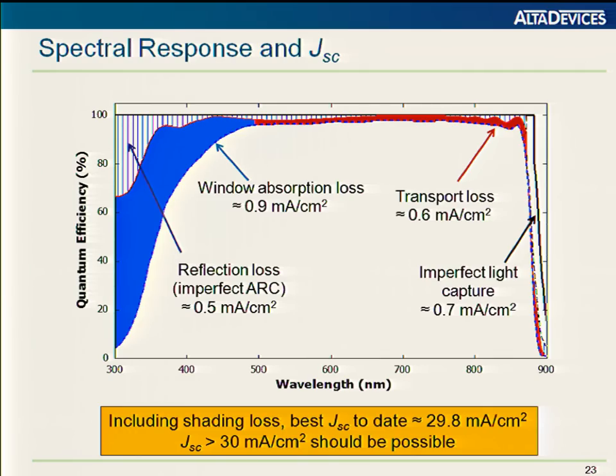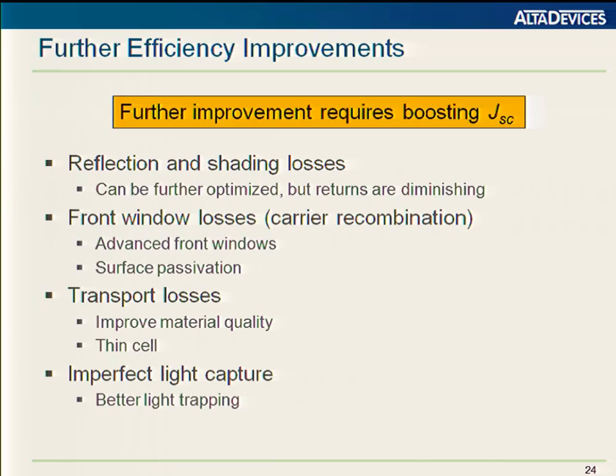And because our cell is relatively thin, we are always trading off JSC versus VOC to achieve maximum efficiency this way. We've never achieved above 29.8 milliamps per square centimeter, and I haven't seen that reported either. But theoretically, above 30 ought to be achievable. I want to just run quickly through how you might think about reducing these losses, boosting JSC. Reflection and shading can be further optimized, but they're probably in the 1/10 of a milliamp kind of range. Front window losses, there's a lot to be gained there, but it's a huge research project. Surface passivation, higher bandgap window materials, more advanced thinking about how you make the front window.